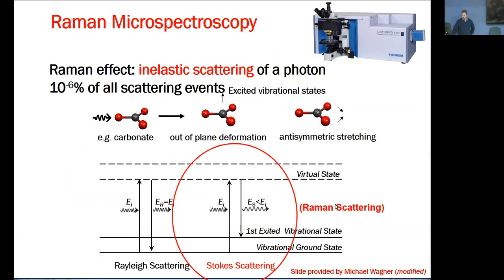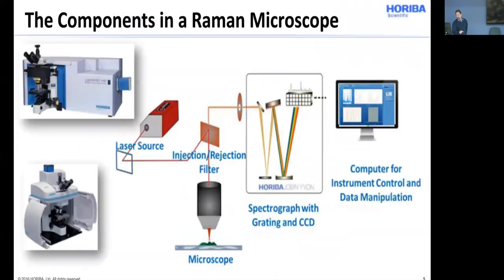In order to get these spectra, we take a laser source, and this doesn't have to go through an objective into a microscope. There are also Raman spectrometers, handheld, that you can hold and you get a spectrum back. But if you have a Raman microscope, you take a laser source, you go through an objective onto your sample, you excite the sample, and then you collect the light that's coming back. You collect a spectrum through a spectrograph, and then you have a computer to actually analyze the spectrum.